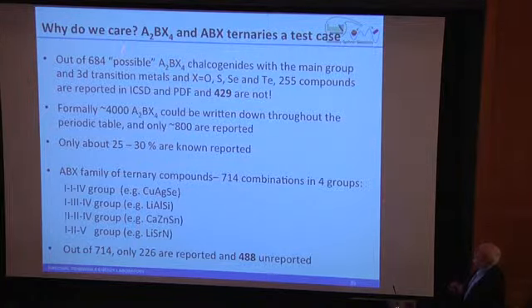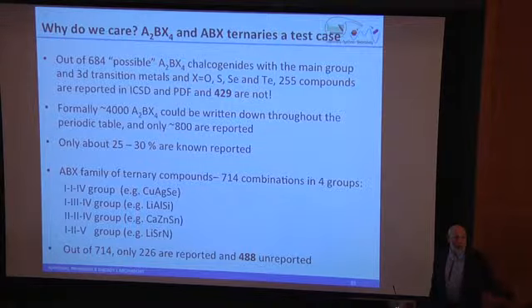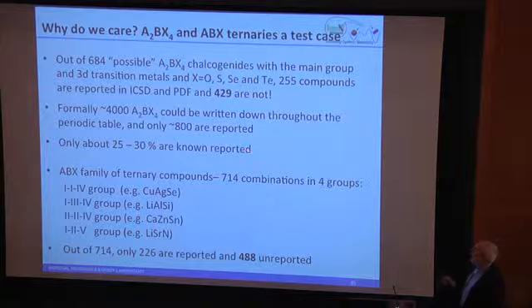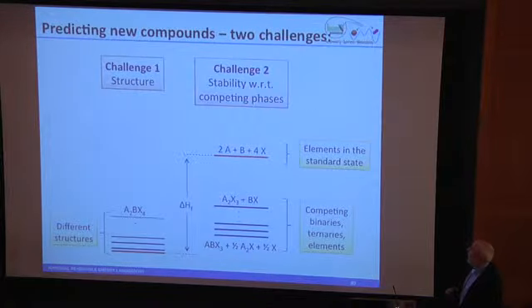So if we look, for example, at the A2BX4 chalcogenides, we only have seen 255 of the materials that could exist in the ICSD, and there's 429 that don't occur there at all. Now, you could first just say, oh, those are all just unstable materials. But in reality, it turns out that's not the case. And so as we calculate these, what we do is we first have to look at what structures are.